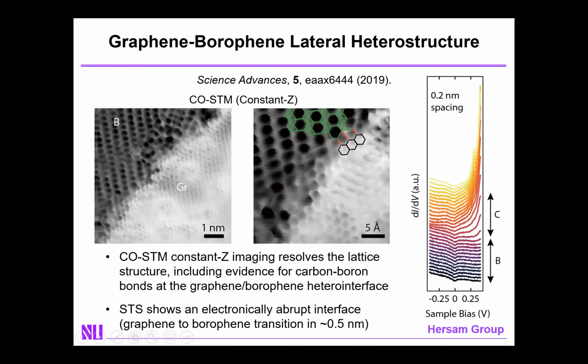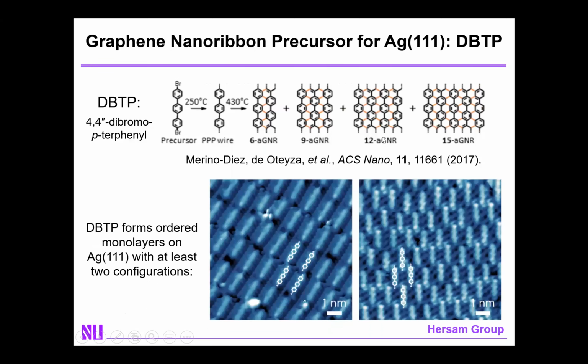The other system that we've gone after is a true boron-semiconductor heterostructure, taking advantage of the fact that it is metallic. And in particular, we went after graphene nanoribbons. The way that we did this was to use a molecular precursor, in this case, dibromo-p-terphenyl, which is known at elevated temperatures on silver 111 to be transitioned into graphene nanoribbons. And indeed, when you deposit DBTP onto silver 111, you see nicely ordered monolayers.